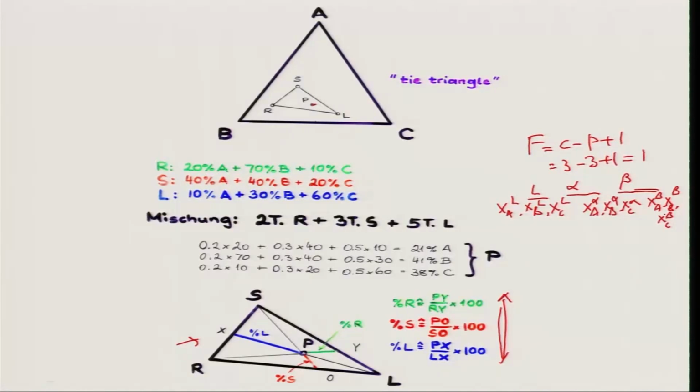And we know that XA plus XB plus XC equals 1 for a particular phase, liquid, alpha or beta. Therefore, we have 6 independent composition variables. The last one is automatically determined by the relationship XA plus XB plus XC equals 1, correct. So, for liquid, XA^L plus XB^L plus XC^L equals 1. If two of the variables are known, then the third one is automatically determined.